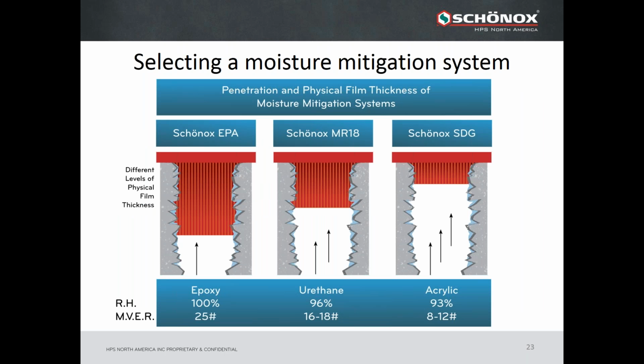Now, if you select a moisture mitigation system, here is a representation or an illustration of what mitigation systems actually provide for us. This is an illustration of a capillary or the porous slab where we show our epoxy EPA, our polyurethane MR18, or SDG, which is an acrylic formulation, and you'll notice that from left to right they have a deeper penetration offered by epoxy down through acrylic. They provide a different physical film thickness which gives you a greater resistance for moisture.